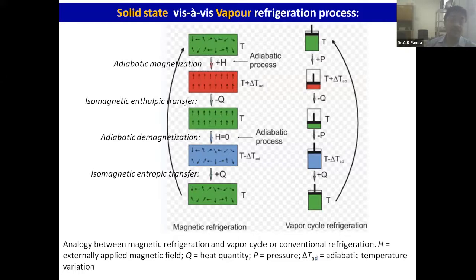First of all, in the very first stage, we have an adiabatic magnetization. When we try to orient it, there is a change in temperature. We raise the temperature of the system. There is of course an isomagnetic enthalpy transfer. After that, we try to draw away the heat at the same applied field. Now the adiabatic demagnetization is the factor when we try to remove the field and it disorients. So this is just to show you how the cycles are correlated more or less.